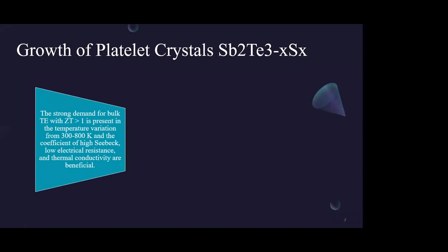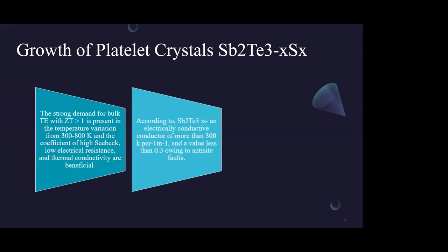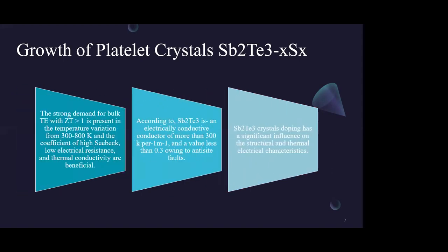So, growth of platelet crystals Sb2Te3-xSx: there is a strong demand for bulk thermoelectrics with a figure of merit greater than 1 in the temperature range from 300 to 800 Kelvin, and a high Seebeck coefficient, low electrical resistance, and low thermal conductivity are beneficial. According to the literature, Sb2Te3 is an electrically conductive material with conductivity of more than 300 per meter and a value less than 0.3, owing to antisite defects. Doping of Sb2Te3 crystals has a significant influence on the structural and thermoelectric characteristics.